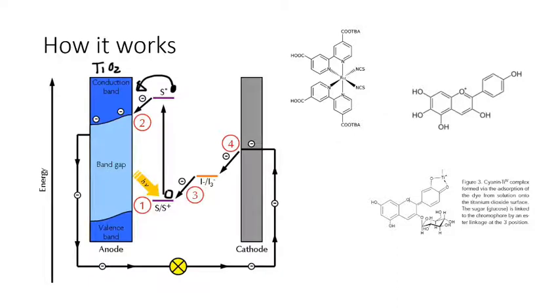through the circuit. When it gets around to the graphite side, that electron can be used to reduce the triiodide to I-, and then that I- can interact with the hole that was left in the ground state of the dye to put an electron back there so that the whole thing can happen again. So the key here is to get the energy levels right between the energy of the dye, so that this needs to be in the visible region, because the band gap of the TiO2 is too big for visible light.